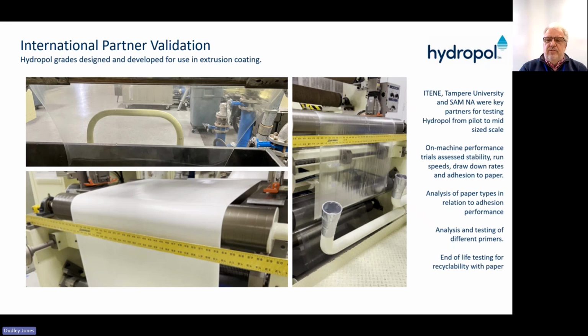On machine performance trials, we assess stability, run speeds, drawdown rates, adhesion to paper. We ran different types of paper with different types of primers. What I will say at this stage is, if we run Hydropol on its own through an extruder, we do need to prime the paper because of the crystallinity of the product when it hits the surface of the paper. We're looking into developments with non-primer, but that's some way off. So you do have to prime before you coat. And then on top of that, once we've done all the tests, we took all of these structures through recyclability and end-of-life testing. So we're running commercially.